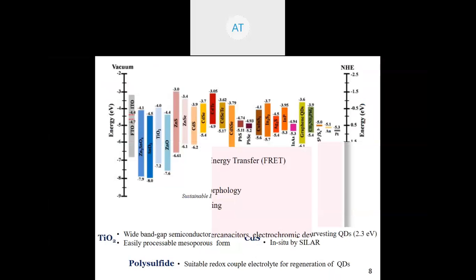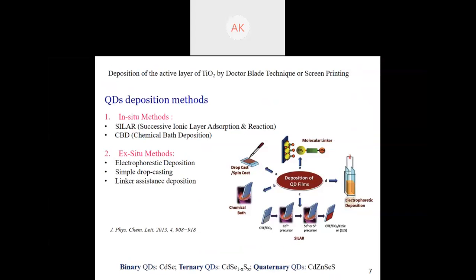So in my lab, I prefer in situ techniques like SILAR or CBD. Why so? Because I feel there is more uniform deposition over the TiO2 film. But I will accept that in some cases, when you have in situ growth of quantum dots, you may have in some places quantum dots that have moved to the nanometer scale. Quantum dots have to be restricted below 10 nanometers. You have certain agglomeration and it tends to grow to 20 to 30 nanometers. So you then may not call it a quantum dot. But you can also use linkers and such to regulate that.